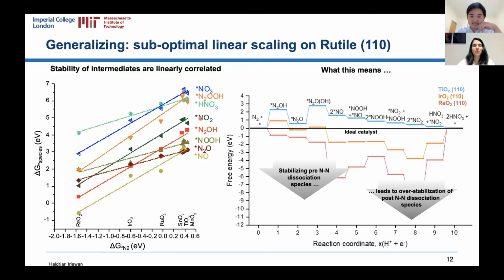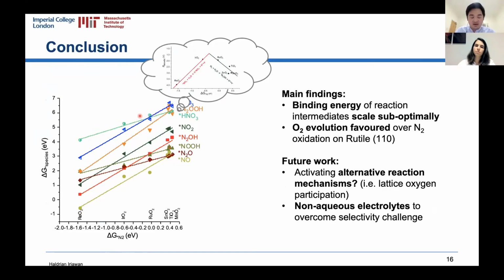Thank you. Yeah, and when you mentioned in the conclusions, for future work, other alternative non-aqueous solutions, do you have any idea of what else you could use? Oh yeah, so for example, the alternative reaction mechanism. In all the steps that we considered here, to make nitrates from nitrogen, we actually get oxygen from water. For an alternative mechanism, we can think about a material system that has very active surface oxygen, such that our nitrogen accepts oxygen from our catalyst surface. So maybe we can explore some very reactive oxides like perovskites or spinel oxides.